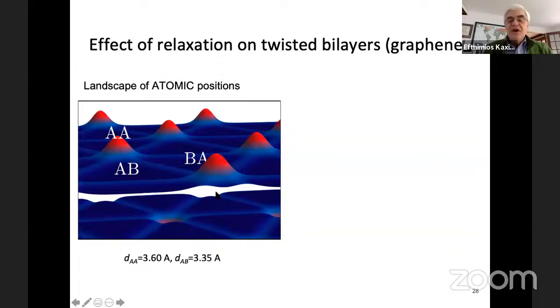So what happens actually? Let me show you two different views of this. This is one of the pictures that Nihat put in this nice poster for my colloquium. This is what happens to the atomic positions. These are the two layers, and I'm showing you the different arrangements of the atoms. In some regions, the atoms have the AB or BA arrangement, and these regions are close to each other, as shown here. In these regions, the two layers attract each other. In other regions, the atoms have the AA stacking that I was describing a moment ago, and in these regions, the atoms repel each other. That's why I'm showing these as little mountains and these as little valleys. So this is how the atoms relax, reform, and readjust themselves under the overall twist that we have imposed on the two layers. And this has important implications for the electrons.